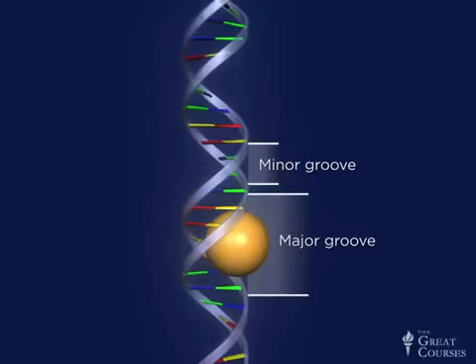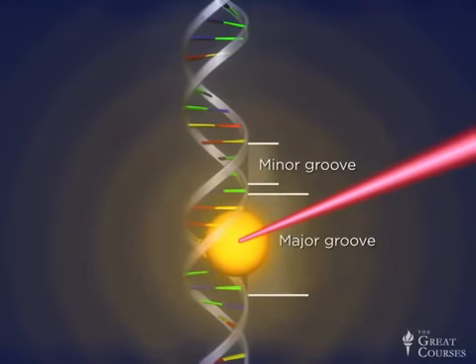So if a 1.4 nanometer gold nanoparticle nestles itself into this major groove space and light causes the particle to give off heat, local heating is going to result. And that heat can cause the two strands to dissociate. And when DNA strands dissociate, well, that really interferes with a cell's ability to function properly. And roughly the same thing can happen with protein molecules. Certain proteins will even non-specifically attach themselves to gold nanoparticles, and these proteins can also be denatured when heat is produced. Really, all cellular structures, which are held together by non-covalent interactions like hydrogen bonds and van der Waals interactions, can be perturbed by heat. So exciting gold nanoparticles with light can basically turn a good detection sensor into a sensor that can both seek and destroy a cell. So let's take a look at an example of how this can work.